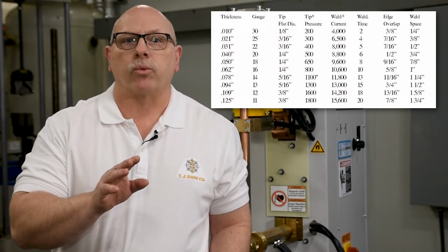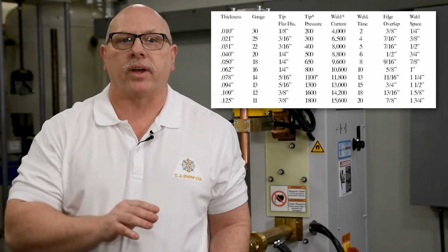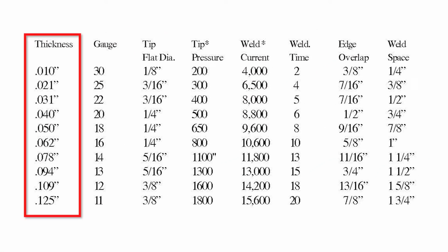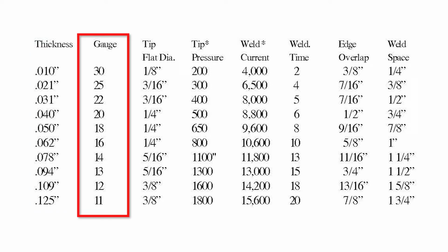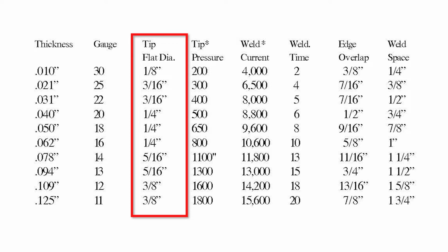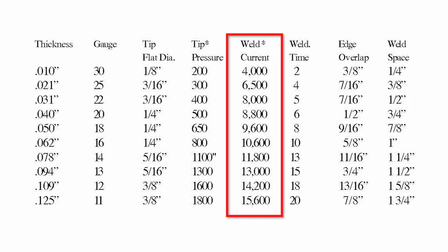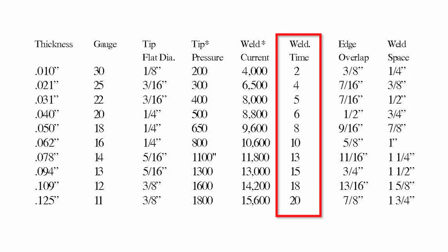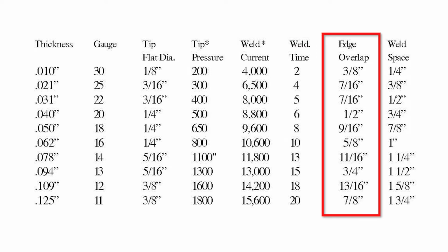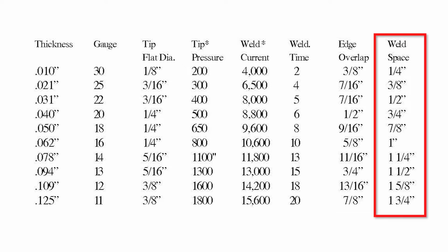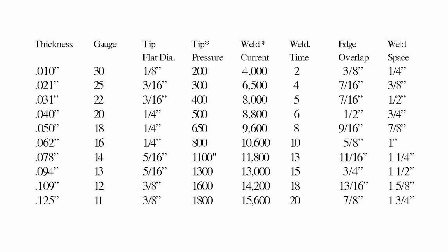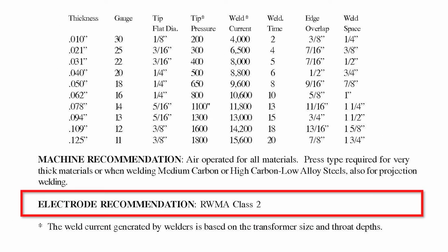The chart assumes that you're welding materials of the same type and thickness. The leftmost column represents the material thickness in inches. And continuing from left to right is the material gauge, recommended tip face diameter, required tip force, weld current requirement, weld time, edge overlap, which is the distance from the edge of the material to the center of the weld, and weld spacing, the minimum distance between welds center to center to prevent shunting. The chart also calls out the correct copper classification for the electrodes being used to make the weld.